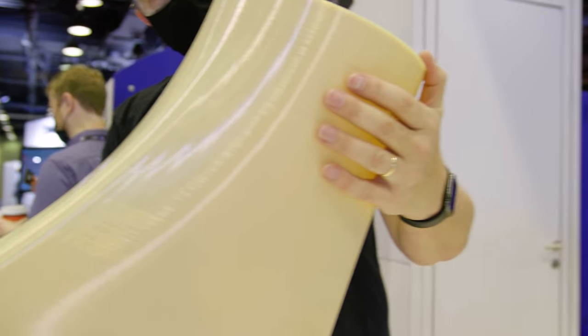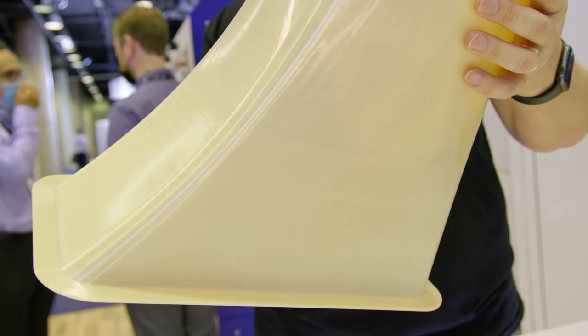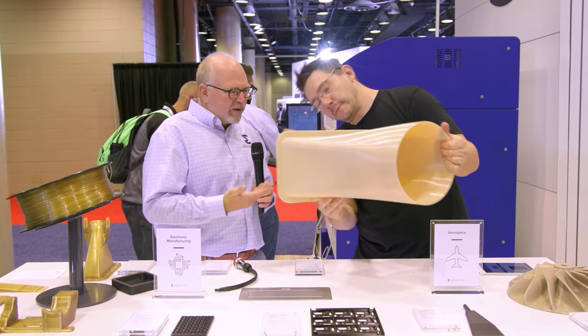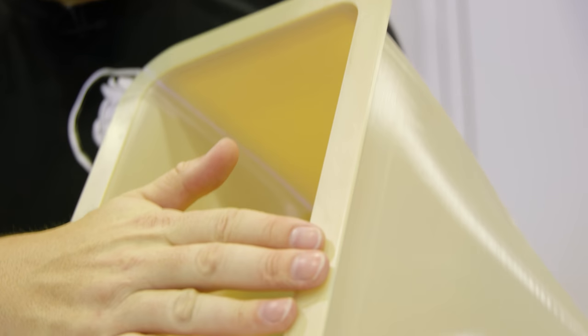Yes. On a competing machine that prints a little over 20 hours, we print that in about 7.5 hours, and this is an Ultem 9085 part. This is Ultem, this is PEI. We print it directly on the bed, which no one else does. So parts like this and the impeller we have are nice and smooth on the bottom. We don't use a huge amount of rafting.